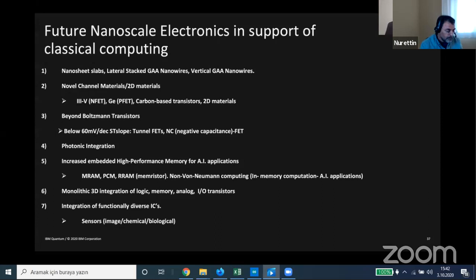Another approach to improve performance further is to introduce materials that have higher mobility than silicon in the channel, III-Vs for NFET, germanium for PFET. And then there's also groups looking at carbon-based transistors and 2D materials. In terms of electrostatics, going beyond 60 millivolts of subthreshold slope, beyond the Boltzmann limit, is being looked at using new physics like tunneling, which has a better slope than 60 millivolt per decade. It's not limited by thermal. And negative capacitance, introducing ferroelectric materials in the high K metal gate.